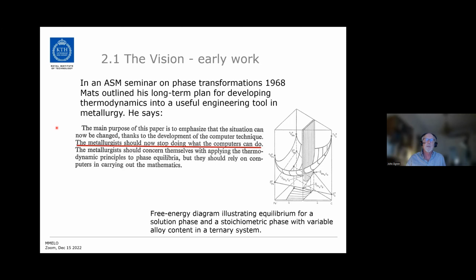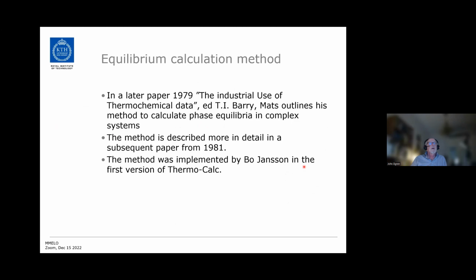carrying out the mathematics. And here is a diagram in a ternary system, ternary Gibbs energy curves in the same paper. And in a later paper, he presented a general method to calculate phase equilibria in complex systems. And this is described in more detail in a later paper in 1981. And this is a method which was implemented by Bo Jansson in the first version of Thermo-Calc.